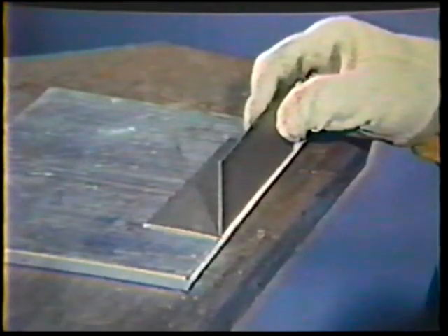To form the workpiece for this exercise, place one piece of 16 gauge steel flat on the table. At the edge, place a second plate perpendicular to the first plate. The edges should be placed together to form an equal joint. Place a small tack weld at the right-hand corner without filler metal. The joint should fit together tightly along its length to reduce the possibility of melt-through. If the edges do not line up accurately, then place a second tack weld at the opposite end of the joint.